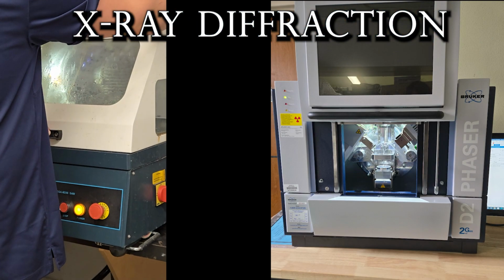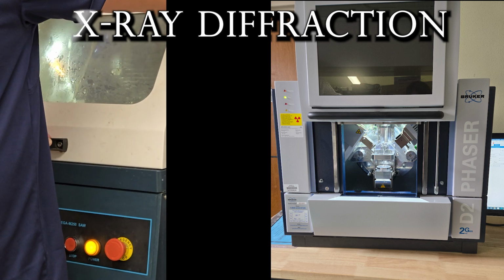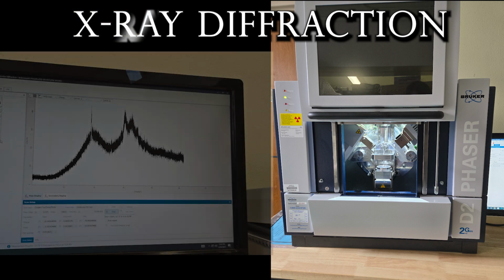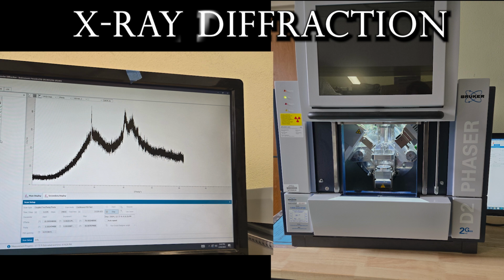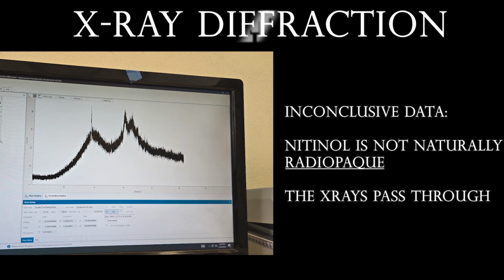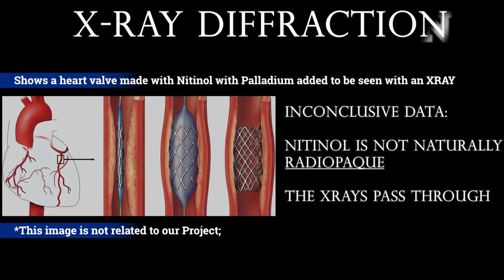We initially used X-ray diffraction to verify the composition of our nitinol sample, but the results were inconclusive. A couple months later, we discovered that this was due to nitinol not being naturally radiopaque, meaning X-rays passed through it directly with minimal interaction. This property explains why in medical applications nitinol is often paired with platinum or palladium to help with medical device imaging.